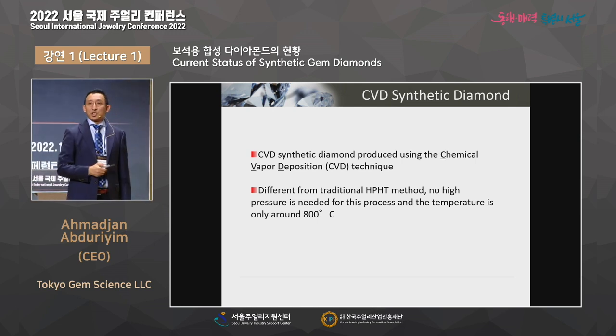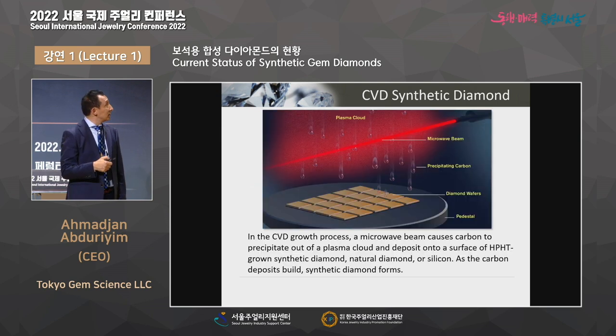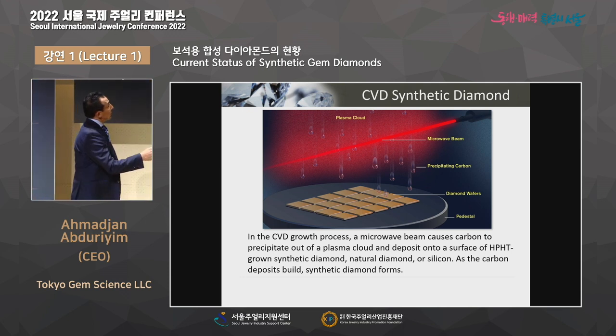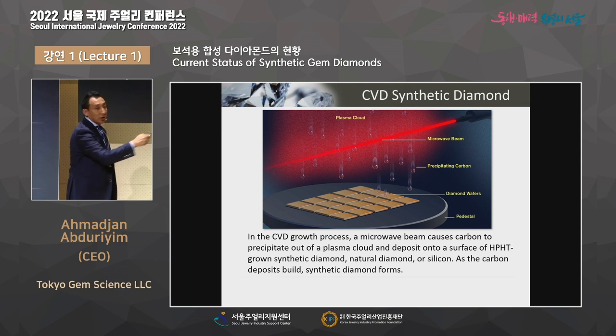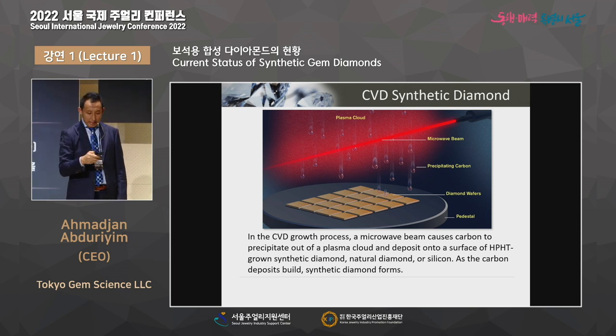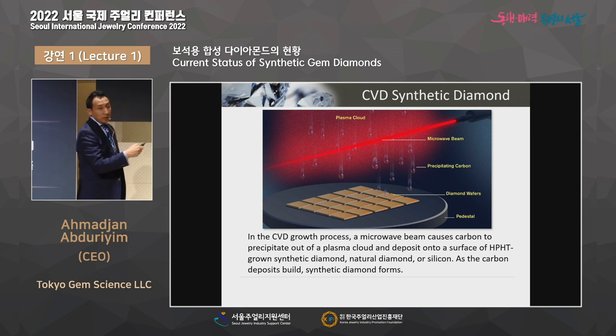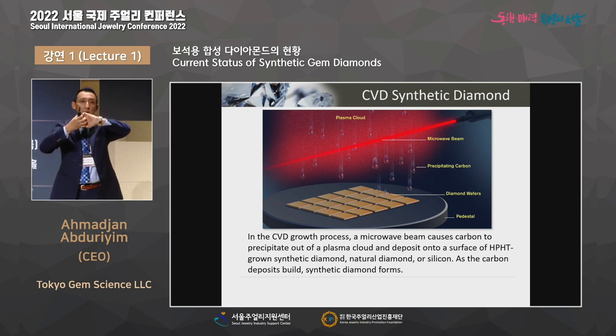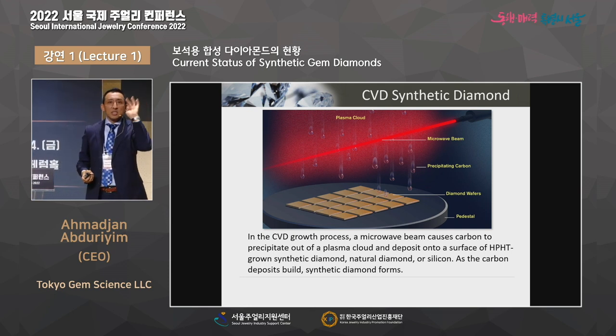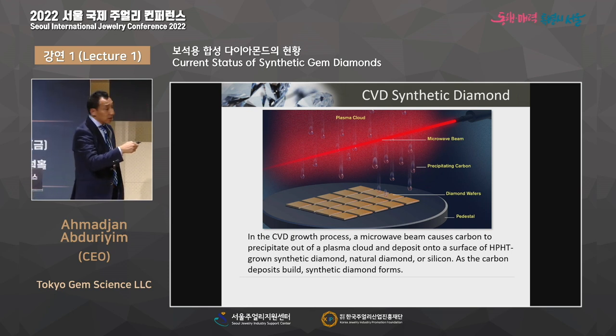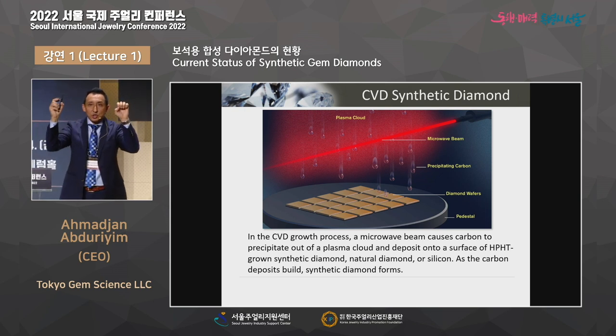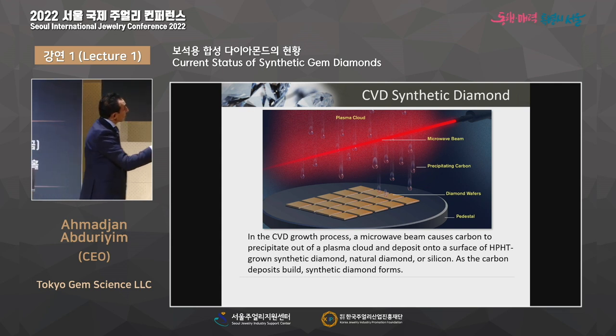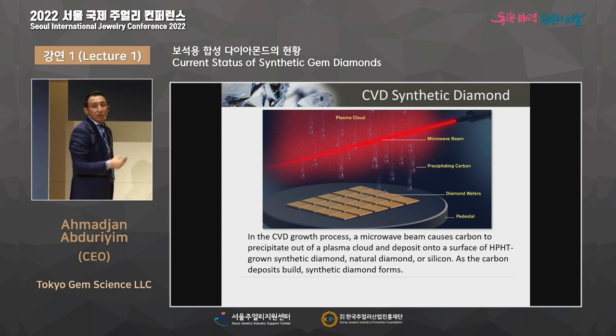They don't need a high temperature. Very simple instrument. Let me show you. This is one of the illustrations to show there is a microwave to create a plasma cloud in this area. It's around 800 Celsius. And we have a gas here to react with each other, like hydrogen with methane gas. They put together to make a chemical reaction that breaks down the carbon with hydrogen. Then they deposit the carbon onto the surface of the seed crystal.